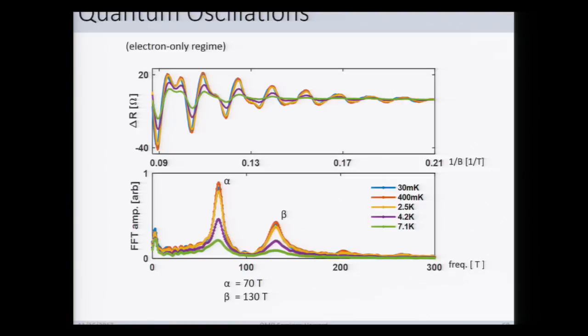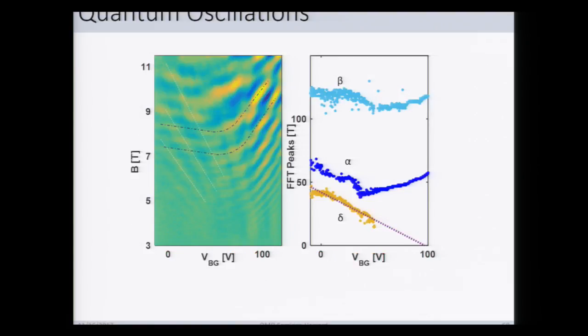And we can then look at how all these evolve as a function of gate voltage, and we can get this map of these oscillations as a function of gate voltage and magnetic field, and do the same kind of Fourier analysis and find that there is this fan, this weaker fan that seems to extrapolate to depletion at around 100 volts, and then we actually have two electron pockets present at high density, which is likely due to a spin-orbit splitting inside the system.